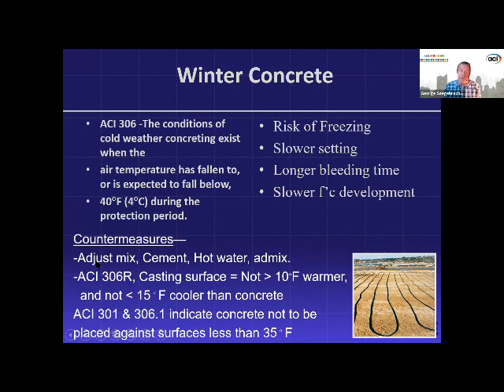And then ACI 306, I'm going to tell you about a paper at the end that I used as my reference from a good friend of mine. I got approval from him to give it to Bob to let you guys look at. Very interesting. That talks about 306, the guideline that suggests not placing concrete more than 10 degrees warmer. The surface that you place the concrete against should not be more than 10 degrees warmer, nor greater than 15 degrees cooler than the concrete temperature you're placing at. And 301, structural specifications for concrete construction, and 306.1, the spec, indicates concrete not to be placed against surfaces that are less than 35 degrees. The paper I'm giving you shows there are some disparities in those two requirements. So without reading the paper to you, I want Bob to give that to you if you want after the presentation's over.